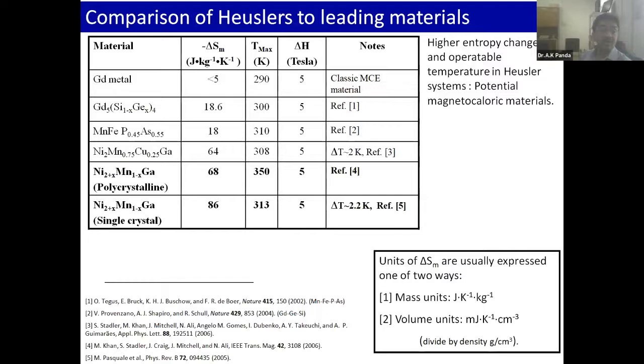Nevertheless, now let us compare some of the previously known materials. One is the well-known gadolinium. Let me tell you that entropy is conventionally mentioned in joules per kg Kelvin. And if you talk in terms of volume units, it is millijoule per Kelvin per cubic centimeter. So these are basically the two units that you find in literature. And going back to the properties, Tmax is where you find the maximum entropy, which lies around 290 Kelvin, with the application of 5 Tesla. And gadolinium belongs to the classic magnetocaloric materials.